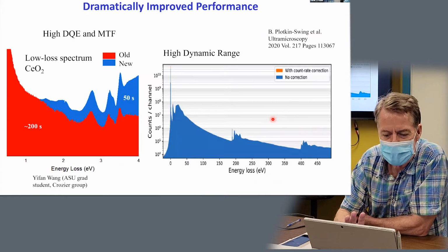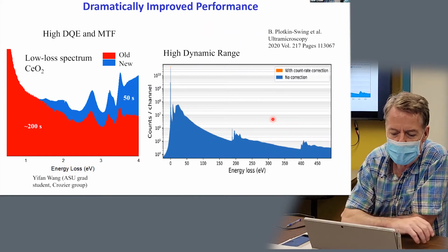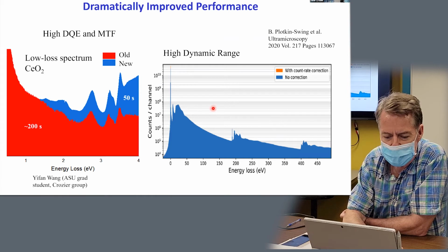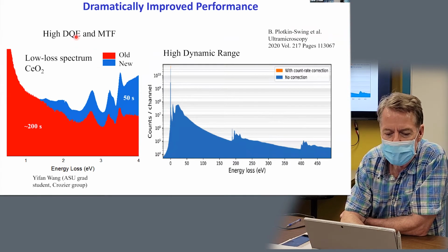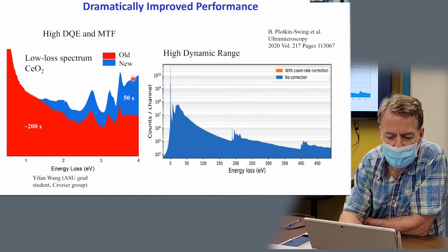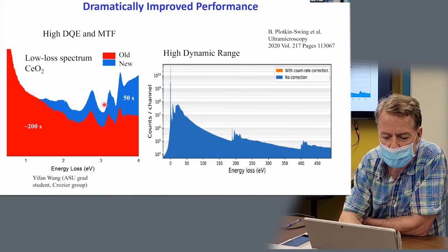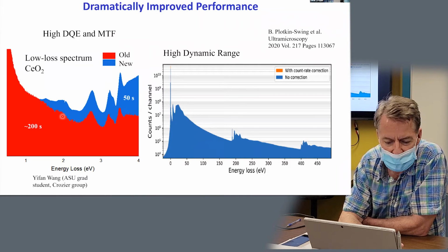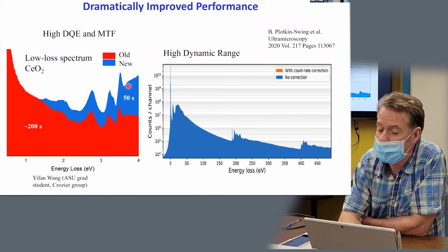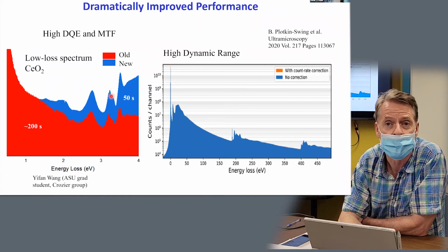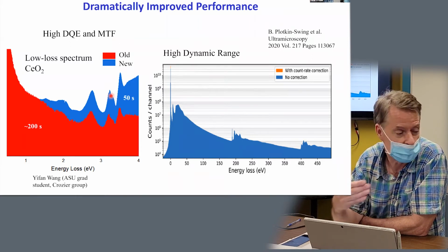Just to show you some practical things, and Shize will show you more examples, but in terms of electron energy loss spectroscopy, this is an example that illustrates the improvement in the sensitivity, the improvement in the DQE, and in the point spread function. So this is a valence loss spectrum from cerium oxide, showing photonic modes. The band gap is about here. These are photonic modes that you can see. The red spectrum was recorded with the old detector, and you can see that it's noisy. It took 200 seconds to record. The blue curve is recorded with the new detector, and you can see that it's a lot less noisy and the acquisition time is less. So that's telling us that we're getting much more sensitivity.